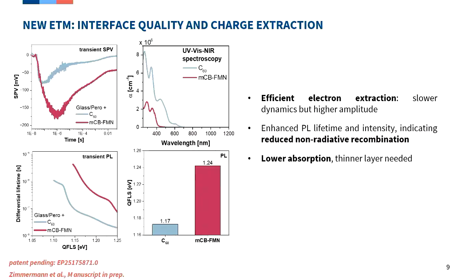So first of all, about absorption. I said that it does not need to absorb. What you see here is the absorption coefficient—the new molecule is the red data, and C60 is the standard, the blue data. You see it has a wider band gap, so there's no absorption in that region, and also the absorption coefficient by itself is much lower. In addition, you can make a thinner layer, so three factors making for a strongly reduced absorption loss.